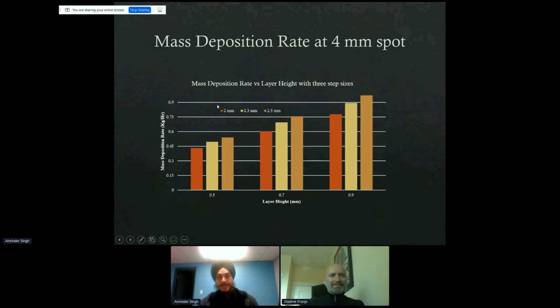So I'll skip this one, but this just shows that at the same spot size, we can vary the deposition rate depending upon the production. The whole motive of showing you the mass deposition rate is that there is flexibility where we can make it faster or slower, but again, depending upon the design and what the material is. There is a range of flexibility of the mass deposition rate. So it's not slow, it's faster. But again, it comes down to the part.